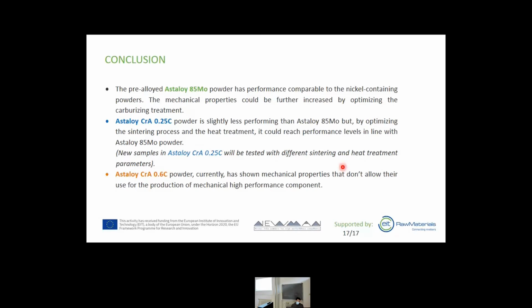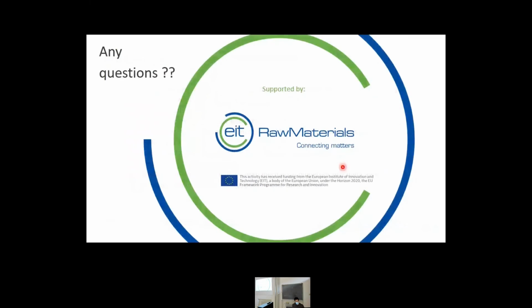Concluding, we can say that the Astalloy 85MO has performances comparable to other nickel-containing powders, and we think that these properties could be further increased by optimizing the carburizing treatment. The second powder, the CRA 0.25, is less performing than the 85MO, but by optimizing the sintering process and the heat treatment, it could reach performance in line with the previous powders. And finally, the Astalloy CRA with 0.6% of carbon has shown mechanical properties that don't allow its use for the production of high-performance mechanical components. Thanks, and if you have any questions, I'm happy to answer.